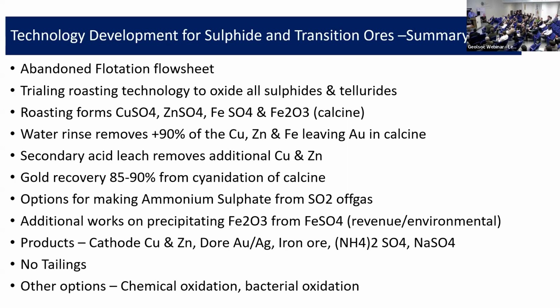It's not so much the gold that's the problem. If you've got a cyanide plant and you need to expose the gold, you've got to get it down to a pretty low sizing, and it's tellurides. So we actually prefer to go on the Albion process. We would probably go for 75 microns. So if you've got encapsulation at 75 microns, you've got problems because it's not going to get that much smaller. 75 would be the cut. Anything above 75 would then go back to the secondary grinding circuit.